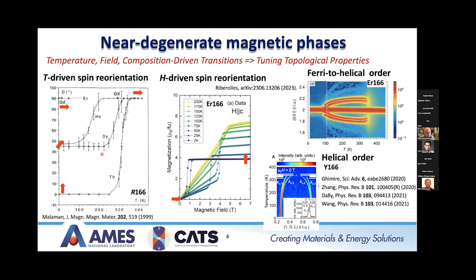For holmium and dysprosium, you see the same thing. You see the spin reorientation transition. You don't end up in the C state. You end up slightly canted away from it. And then erbium, I'll talk about later in the talk. This is actually a little misleading here about the erbium. Not that we don't have a spin reorientation transition, but just that the erbium is not always ferrimagnetically ordered. And then the gadolinium, of course, remains easy plane.